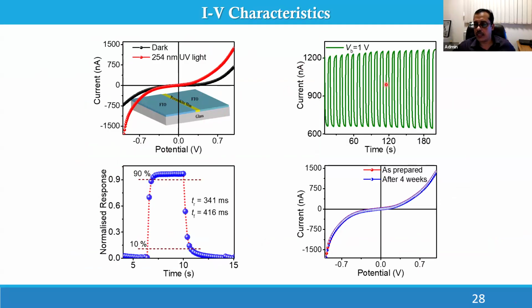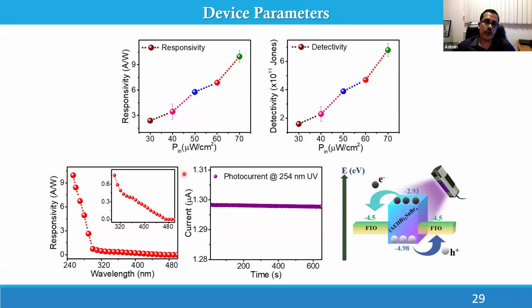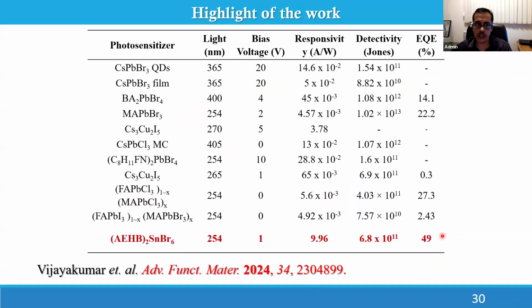And it is giving a consistent current, and this is giving stability analysis after as prepared and after 4 weeks. And this is a responsivity and the detectivity. These are the parameters of characteristics of a photodetector device, and responsivity and photo current for an extended period of several minutes. And this is the simple structure we used, an FTO electrode, and deposited the material between the FTO electrode, and the electrons will jump to this, and holes will jump to the other part, and we are applying a small bias to drive the electron and holes.